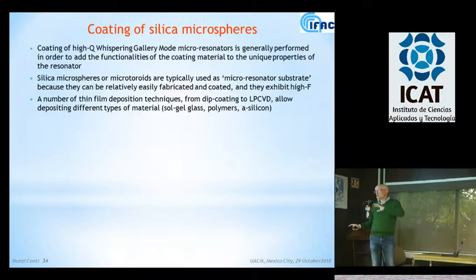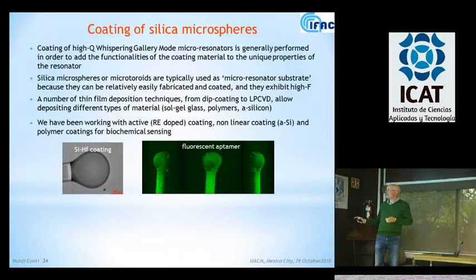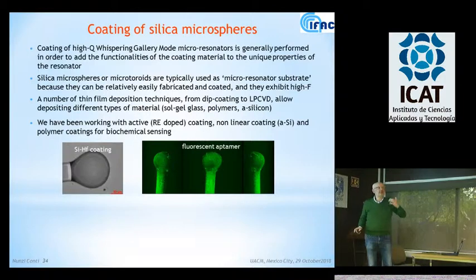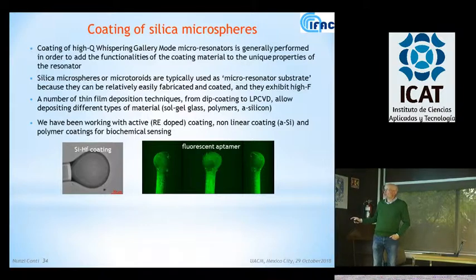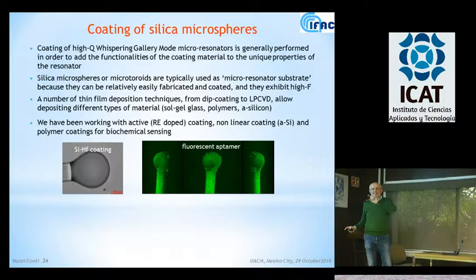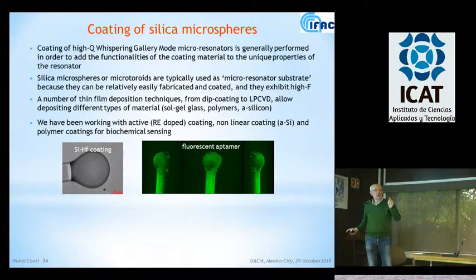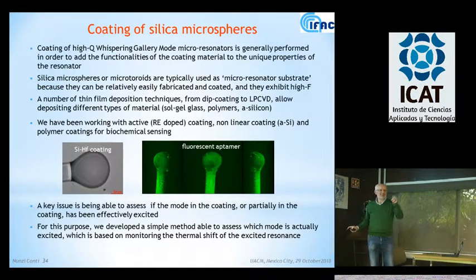And finally, we have been working a lot on coating of these spheres, because basically you can think that if you want to assess the property of some material, you can use the spherical structure of your silica, and then you can coat it. So basically, it means that you add the functionality of the coating material to the properties of this high-Q resonator. And we have been working with sol-gel glass, with polymers, with amorphous silicon. And in any case, here it was really critical to demonstrate that we were coupling the coated part and not the inside by tunneling, which has been reported sometimes, showing that if you want to use the property of the material, you need to couple light in the material.